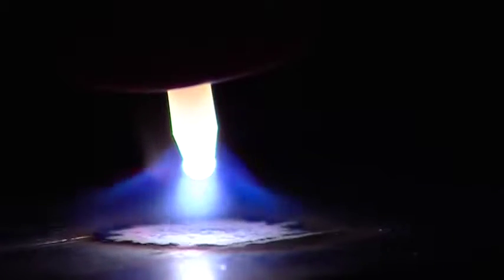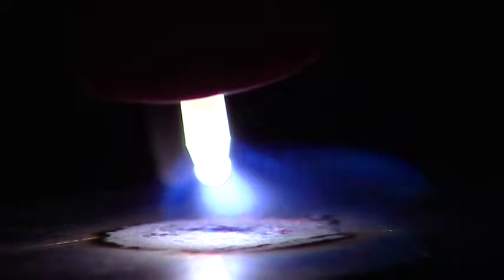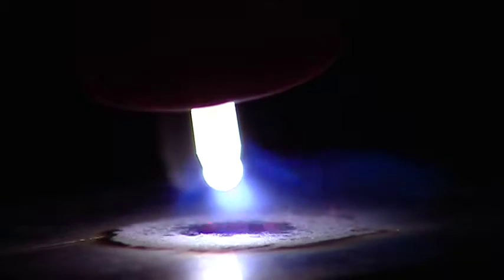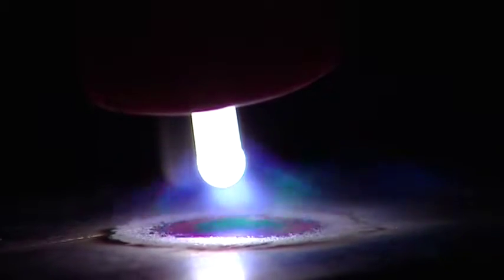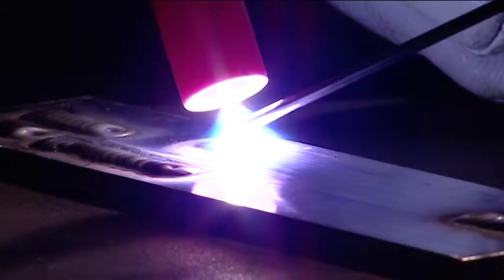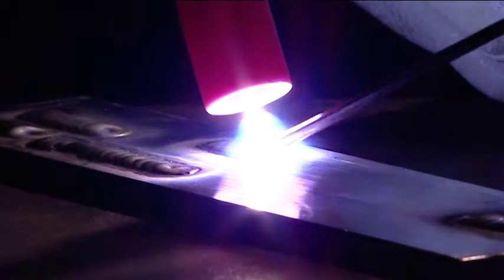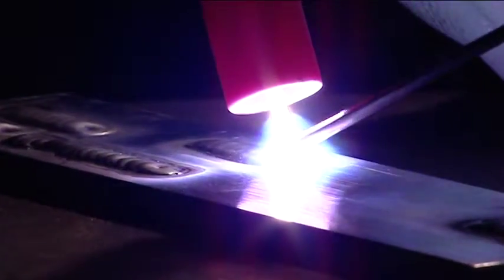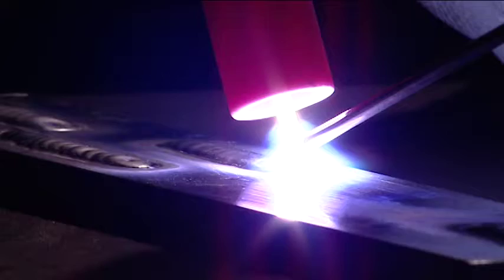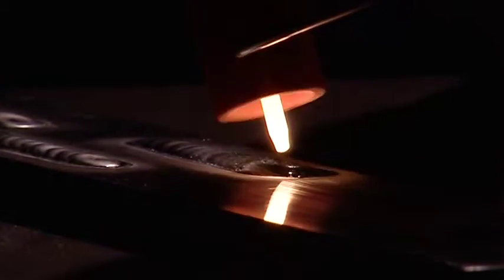Another result of having the balance set too low is tungsten balling. What this means is your tungsten will melt back and not stay sharp. When you have the AC balance adjusted correctly, you'll see a bright, shiny puddle without anything floating on the surface. You'll also be able to maintain a pointed tungsten.